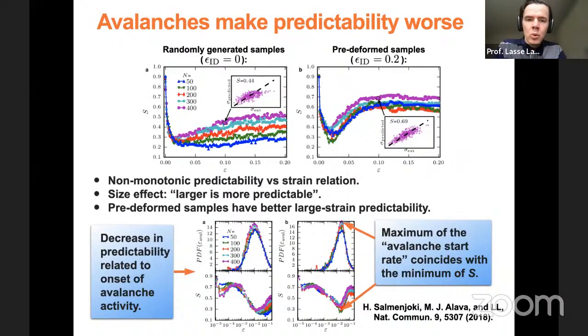Then we can try to understand why this predictability curve looks the way it does. You see that there's this non-monotonic predictability versus strain relation. We think that is related to the onset of these deformation avalanches. You can look at the distribution of the starting strains of these avalanche events, and it looks like this. You have a peak here: at some intermediate strain, you will typically generate lots of avalanches. Then it goes down as you keep increasing strain, because the avalanches get bigger and bigger, so there will be a smaller number of them per unit strain.